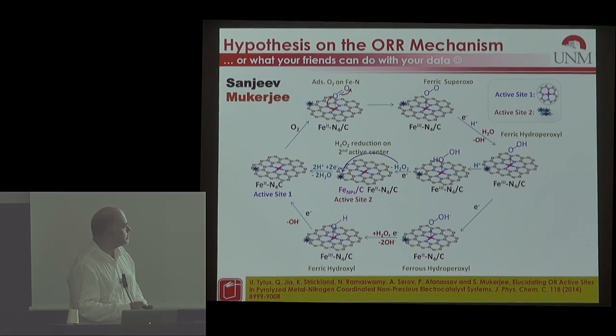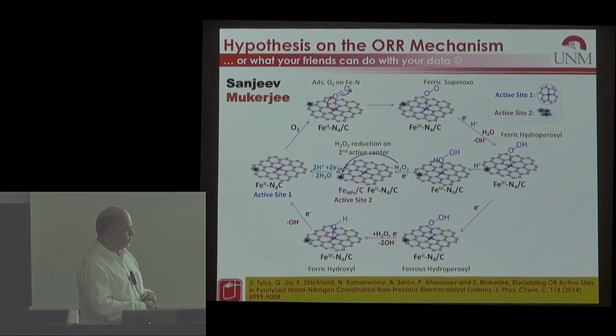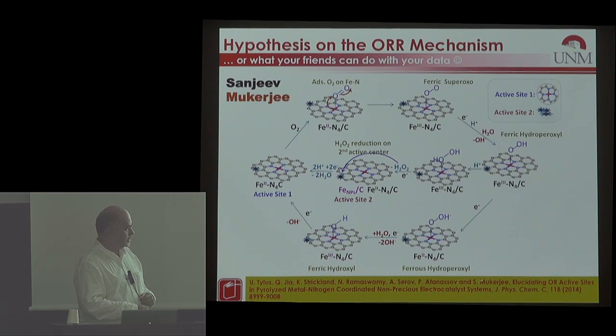That also allows us to produce a hypothesis of the catalytic mechanism that involves binding of the oxygen on the metal and a secondary active site. And this secondary active site in this particular paper is not specified, because this paper has two principal authors, and these two principal authors didn't agree exactly on what this active site is. And I'm going to tell you who thinks what, okay? Because I'm right.